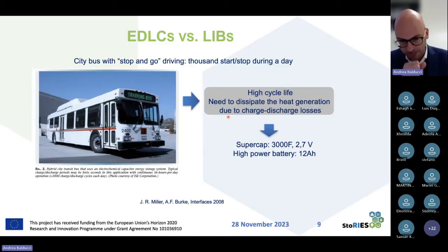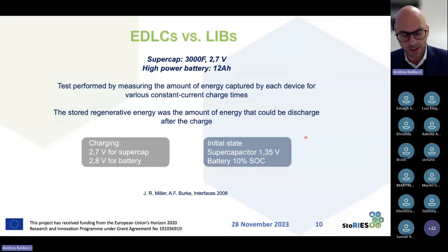In this study, Miller and Burke were comparing two systems: supercapacitors of 3,000 farad, which is an important point, since when we are talking about supercapacitors we normally present the data in farad, with an operative voltage of 2.7 volt, against a high power battery which had 12 ampere hour of capacity. To realize this comparison, they performed tests in which they measured the amount of energy captured by each device for various constant current charge times. The stored regenerative energy was the amount of energy that could be discharged after the charge.